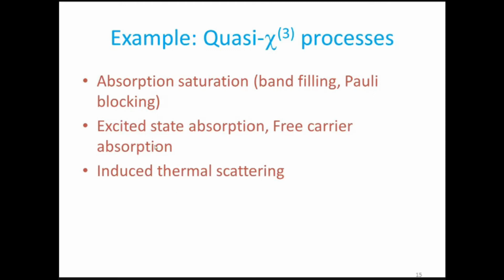Now, similar to that, there is another thing called excited state absorption, free carrier absorption, and all that. So here what happens is, when you apply light into the system, the molecules get excited to higher energy states, but then those energy states start absorbing. So that is what we call excited state absorption. This is common in molecules, organic molecules, polymers, and all that. And free carrier absorption is in the case of semiconductors and metals. So there also this is quite possible. Then there are effects like thermal scattering, which are because of the heating effect of the laser radiation in a system.